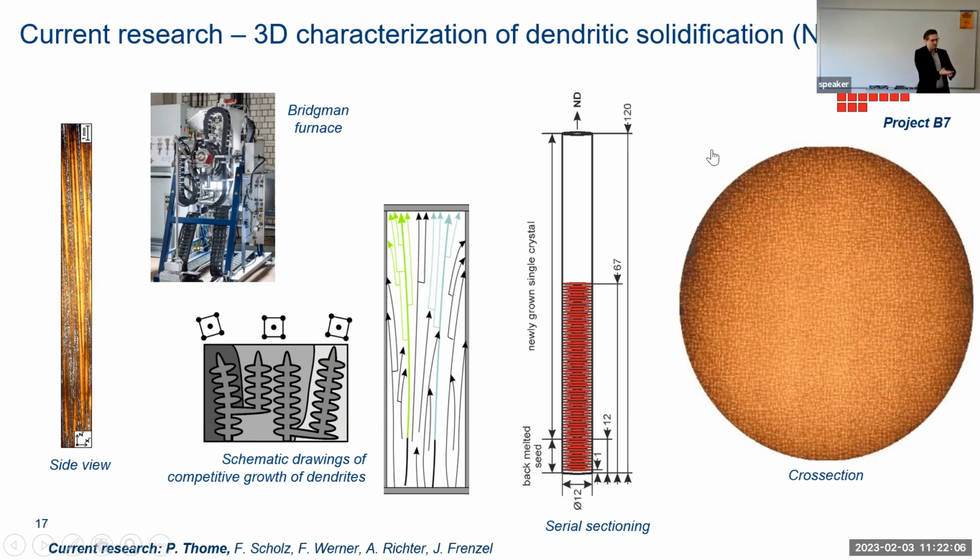You put the sample, you melt it, you cool down one side, and you slowly pull out the sample, thus creating a temperature gradient, and the crystal is forced to grow. It can only grow in one direction. We use a seeding technique. There's also a helix, a grain selector technique, but I don't want to talk about this much.